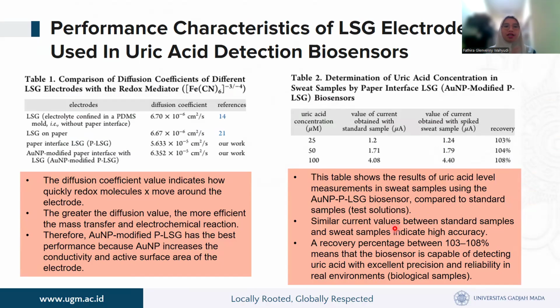And we got the table. This is about performance characteristics of LSG electrodes used in uric acid detection biosensors. Table 1 is about comparison of diffusion coefficients of different LSG electrodes with the redox mediator, potassium ferrocyanide and potassium ferricyanide. The diffusion coefficient value indicates how quickly redox molecules move around the electrode. The greater the diffusion value, the more efficient the mass transfer and electrochemical reaction. Therefore, AuNP modified PLSG has the best performance because AuNP increases the conductivity and active surface area of the electrode.